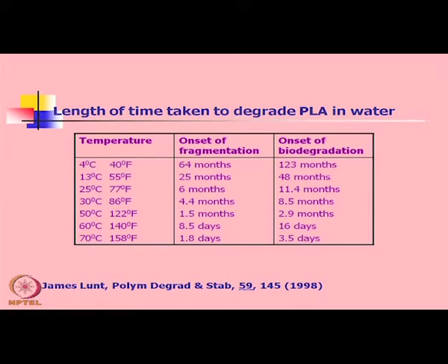After fragmentation, through hydrolysis of those hydrolyzable bonds, microorganisms can perform at a faster rate. So, this shows the time period at different temperatures. Say, if you do the degradation or fragmentation at lower temperature, the time requirement is quite high, whereas if the temperature is increased, this fragmentation will be much faster, from 64 months it has come down to say 2